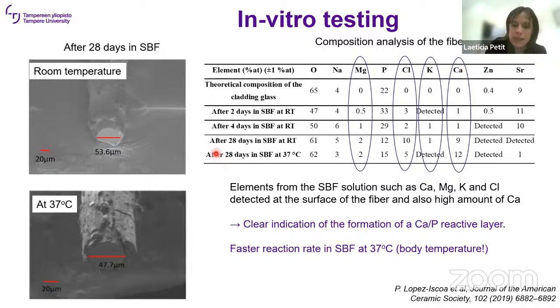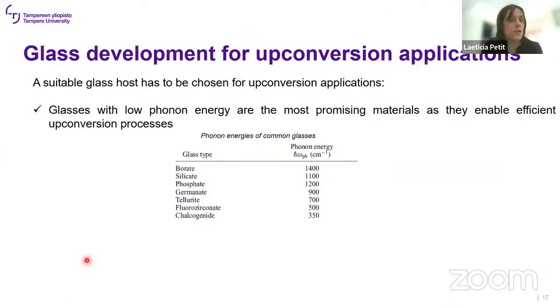And so we did the experiment at 28 days at 37 degrees C, so the body temperature. And then we have a faster reaction, so a larger amount of calcium, and the fiber is way smaller also. And this is indicating a faster reaction rate in SBF at 37 degrees C, as you can expect. So this is a promising glass composition for tracking in vivo the reaction of the glass with the body.